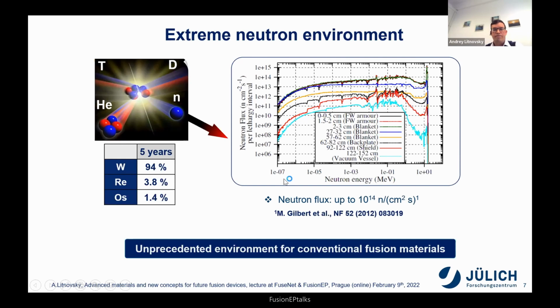Speaking about the neutron flux, here we see the neutron flux density as a function of energy per lethargy interval. We can see that for 14 MeV neutrons, the fluxes can be as high as 10 to the 14th neutrons per square centimeter, which is really a great number. This is a really challenging environment, which will change the properties, I would say honestly change, because it may influence the material one way or the other. And this was speaking only about the so-called regular operation.